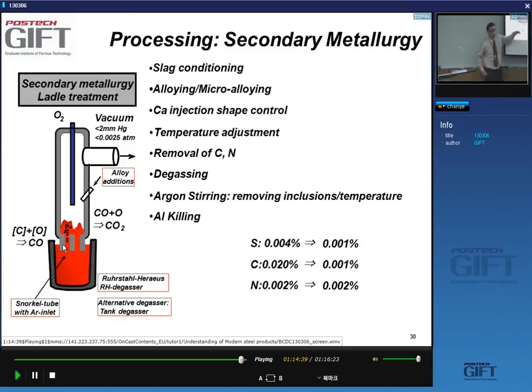And when the metal is here, it's basically in a vacuum, yes. And in this vacuum, the CO that is still in solution reacts with some of the oxygen we inject to form CO2. Okay? And because of the low pressure system, we can continue reducing the carbon. In this system, we also do alloying additions.